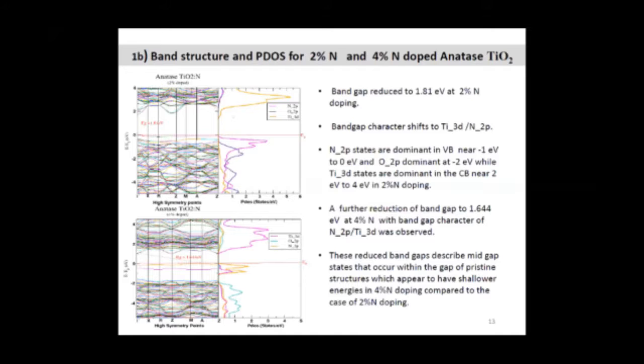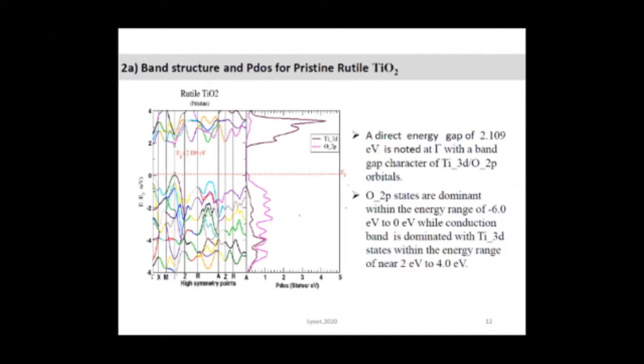However, at 4%, we can see some impurity states within the intrinsic band gap of the materials. These impurity states have been observed to act as recombination centers, so they make the materials not very good for applications in catalysis and photovoltaics. We observed that. And when we checked the pristine rutile structure, it had a direct band gap of 2.109.